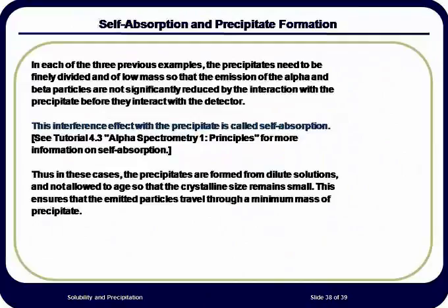This is particularly critical in alpha analysis, as alpha particles can be completely stopped by a very thin slice of matter. Thus, when we prepare a lanthanum fluoride precipitate for uranium analysis, the final precipitate mass is on the order of 1/10 of a milligram. This is not enough to see or weigh, but it can be reproducibly filtered if the chemist uses the correct technique.